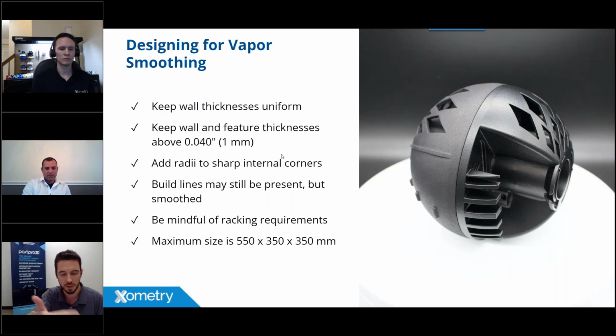But when you are hitting 1 millimeter or below, it doesn't take a lot of energy to fuse those few layers together in powder bed, for example. So that feature becomes almost like a sponge for vapor smoothing. The vapor will move into the surface and just hang out. There's not enough material to actually grab and start moving and pull together, which we can on all the other surfaces. And then when we extract the vapor out, it just comes right out of that sponge. If you get too thin, nothing really has happened because of the very high porosity. That's why 1 millimeter is highly recommended as the minimum thickness.